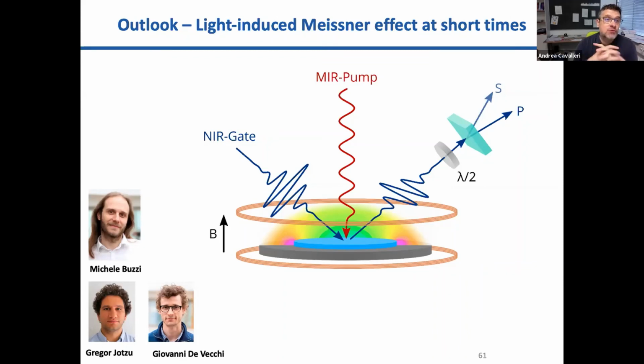Of course, in the other case, we could do these experiments in a large magnetic field. At the moment, we have a 5 Tesla magnet that we bought at the supermarket for magnets. But of course, if you could synchronize a pulsed magnetic field with a laser, you could consider doing these experiments. Of course, there are issues of repetition. We talked about this with Paul Goddard 10 years ago when we were talking about FELs. There are duty cycle considerations. These experiments are done by doing the experiment 1,000 times a second and acquiring for a long time. If you can pulse your magnetic field once a minute, you better have an experiment that has a high yield. So practical considerations notwithstanding, if you can buy a large DC field, lots of things can be done in this regime.